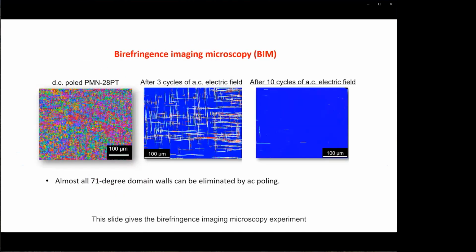This slide gives the birefringence imaging microscopy experiment for the AC and DC poled PMN-28PT crystals. Here the colors indicate the domains with different directions of polarization. It is clear that a very high domain wall density is present in the DC poled sample, while the domain size becomes larger after AC poling. After 10 cycles of AC electric field, a nearly single domain pattern can be achieved in the PMN-28PT crystal.